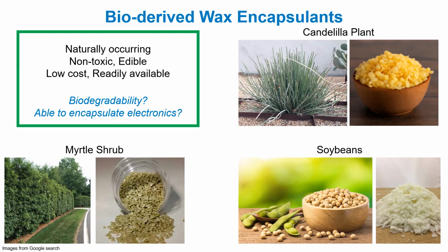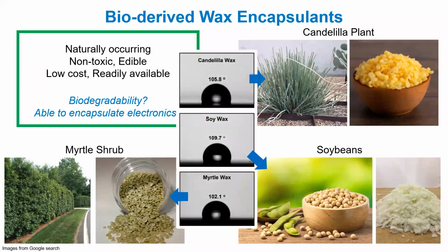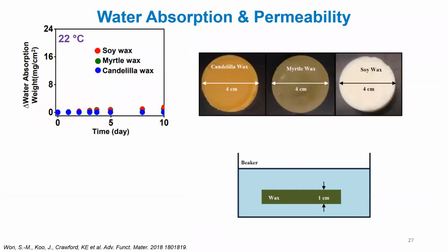These are waxes. And naturally, we know, of course, these waxes should be hydrophobic, and we measured that with goniometry. And indeed, they have similar hydrophobicity, similar water contact angles, and that doesn't really help us out very much. We want to know which of these is better, or maybe they're all the same. We don't know yet. So we decided to make pucks of these wax materials and put them in water and see how much water they absorb. But at 22 degrees, that didn't really give us much information either. None of them really absorbed very much water.